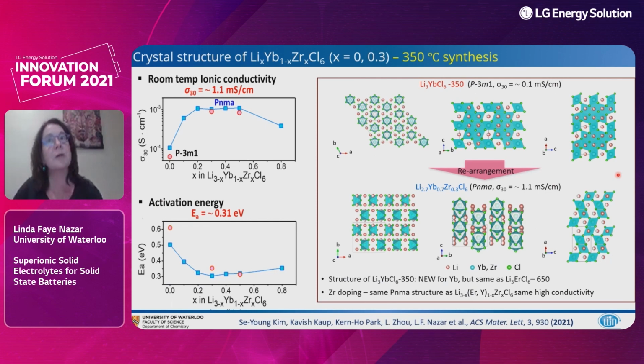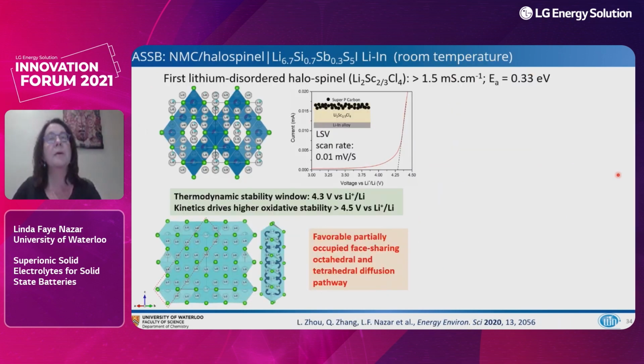How do we make these materials better? So the way we make them better is developing a completely different structure, which is, to our knowledge, the first halo spinel. And it has the formula shown here. It has conductivity even that can exceed 1.5 millisiemens, and again, a low activation energy. It has the same onset of oxidation potential that most of these other halides have, so a thermodynamic window of about 4.25 or 4.3, but the kinetics actually drive a higher oxidative stability of 4.5, as I'll show you in a second.